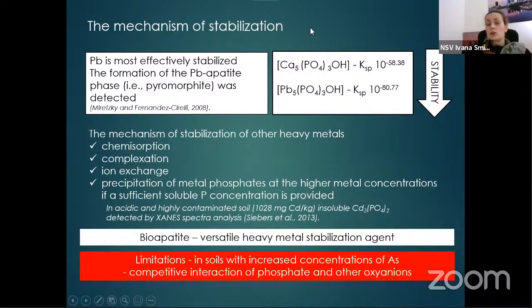The mechanism by which the various metals are stabilized in the soil is different for particular heavy metals. There is a reason why the lead is most efficiently stabilized in all soil types. Namely, this can be explained by the large difference in the solubility of the calcium phosphate and the lead phosphate. And this difference acts as a driving force for the dissolution of calcium apatite and for the precipitation of the lead apatite, which is called pyromorphite.